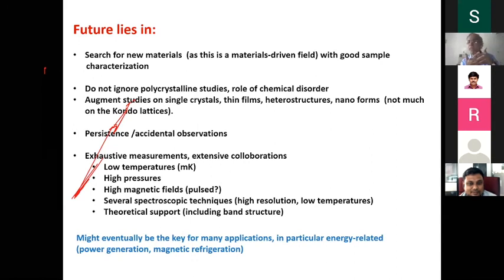You have to augment. Thin film studies are completely open. Heterostructure studies, you can do a lot. Very little has been done. We have done some work on nano forms, in a very crude way by pulverizing material, but that is not the right way to do it. Heterostructure is completely open. And if you persist carefully, there are many accidental discoveries. You have to go to low temperature, high pressure, high magnetic field. You have to apply several spectroscopy techniques, and you get a lot of theoretical support. My feeling is that it will eventually be a key for many applications, particularly for the energy related issues, power generation, magnetic refrigeration, magnetic recording, and also permanent magnets. There are a lot of things that could be done. The future is still open, the field is still active.